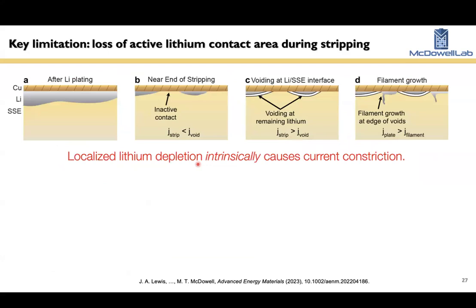So what we think is happening is shown in this schematic. Basically, the difference between a lithium excess cell and an anode-free cell is that at the end of stripping, you're trying to get rid of all the lithium that's present in the anode-free cell. You want to remove all of it from the interface. And so if you have a situation, which we think is pretty much always the case, where there's somewhat non-uniform lithium across the interface, like this, when we get towards the end of stripping, that means that we're going to have some regions that are fully stripped of lithium and contacting between the current collector and the solid electrolyte, and other regions where there's still lithium remaining.